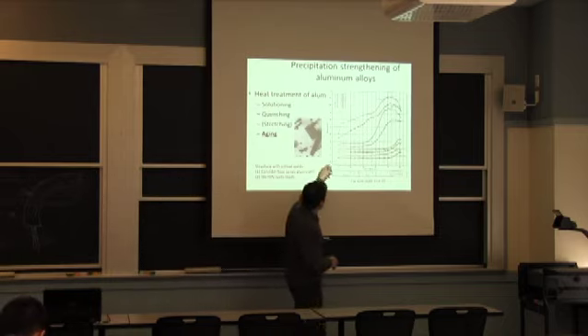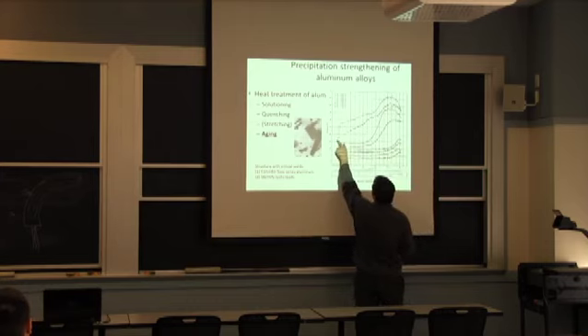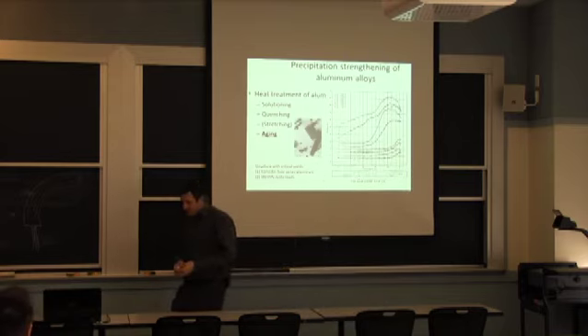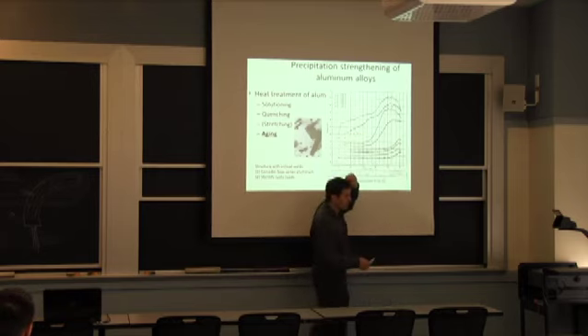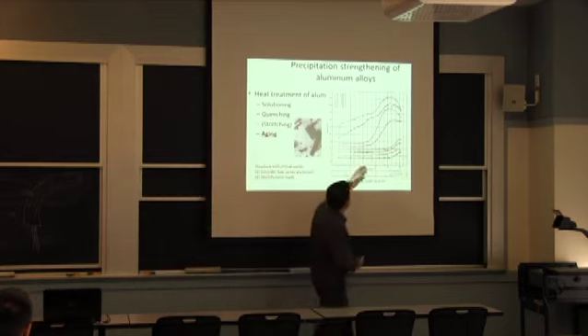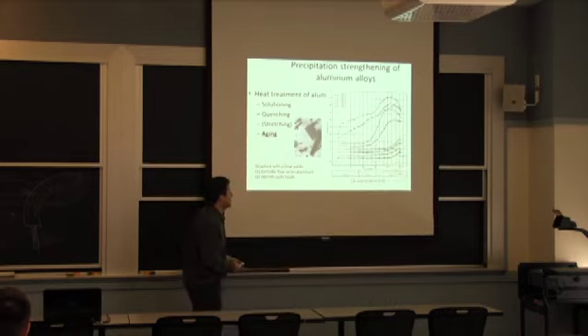The type of hardness evolution you get, a bunch of curves here for different aluminum alloys. So let's just go with the higher copper content. Our hardness goes from 55 Rockwell B all the way to, say, 95, but it goes to a peak at 110. Well, that's kind of the story of aluminum alloys, you can use them in any of those states. And we use the designation T for the treatment that's applied to it. If you have a T6 treatment, it means you're at the peak. Anything before 6 is typically below, and T7, which is not uncommon, especially for 7000 series, is after.